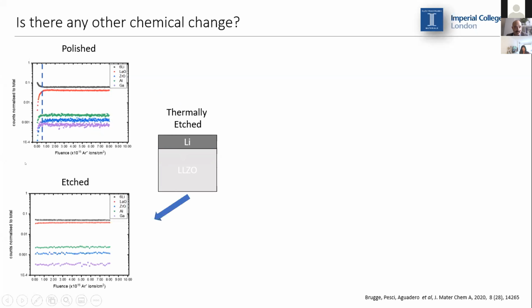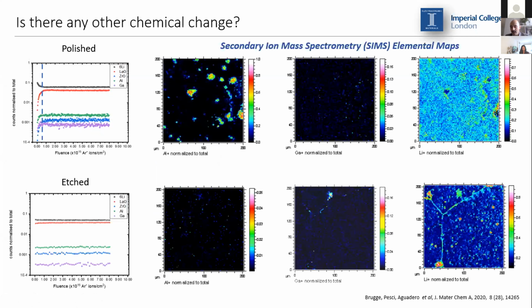And if we take the same sample, thermally etch it, and repeat the SIMS, we actually see that we don't have anymore the corrosion layer on top of the sample. So far we were happy. We thought, okay, it's confirmed, it's a cleaning process. However, we looked more deeply at the SIMS map.